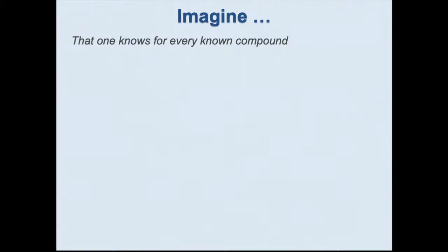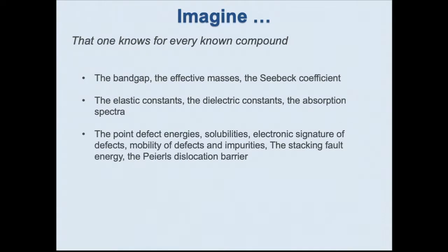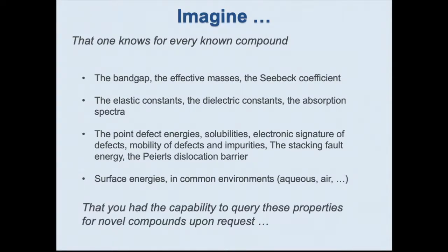So imagine that you kind of knew everything. That you know the basic properties of every known compound, that you would know the band gap and effective masses, Seebeck coefficients, electron mobilities, whatever you want, that you would know the full elastic tensor, the dielectric constants, maybe absorption spectra, point defect energies, solubilities, the electronic signature of those point defects. And then if you're into mechanics, maybe you want to know the stacking fault energies, the Peierls dislocation barriers, and things like that. Maybe if you're into nucleation, you want to know surface energies in air, in aqueous environments, and that you had the capability to query these upon request.